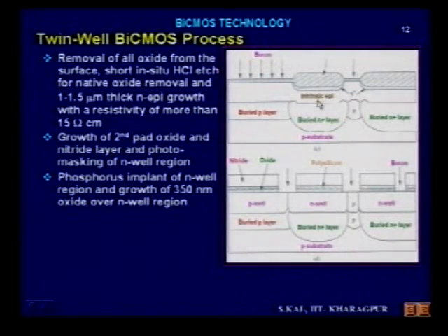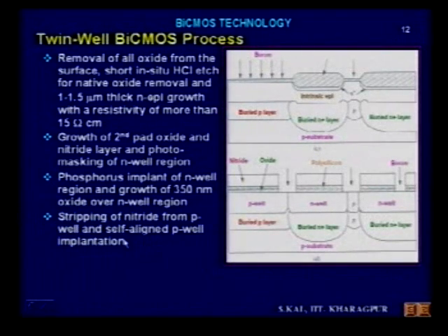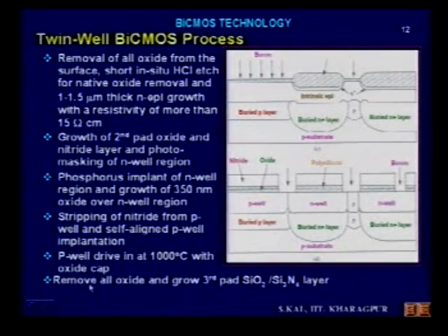You see this region is driven in here. Next step is stripping of the nitride from the P-well and self-aligned P-well implantation. P-well drive-in at 1000 degree centigrade with oxide cap. You remove all oxide and grow third pad SiO2, Si3N4 layer.